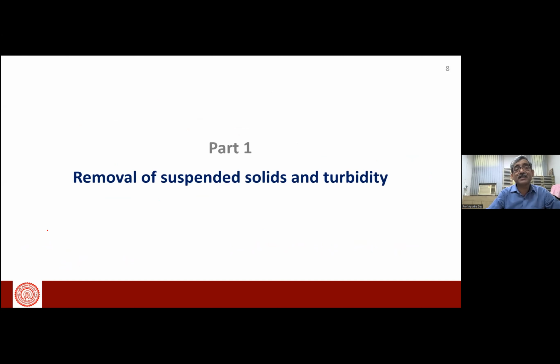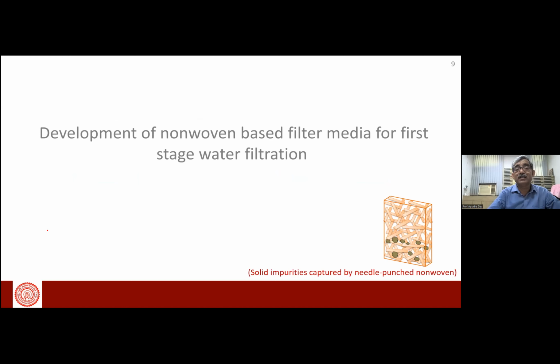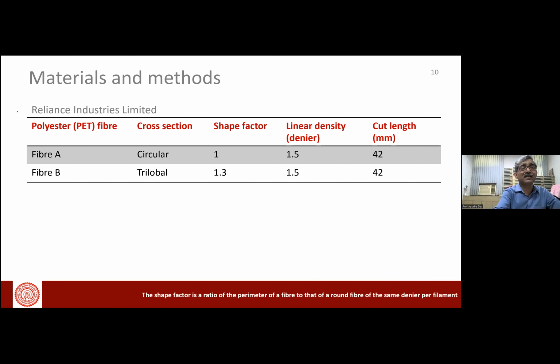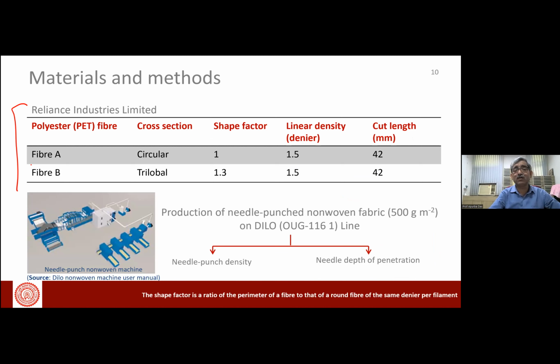So the first thing is the removal of suspended solids and turbidity, the larger particles we wanted to remove. Here we have used the wicking characteristics of non-woven fabrics. If turbid water is at the bottom, and the water flows against gravity, it will resist all these larger solid particles. So in the first stage, against gravity and using the wicking characteristics of non-woven, we tried to remove the turbidity. We have done some experimental plan. I am not going in depth in all this. We varied the needle density and depth of penetration.